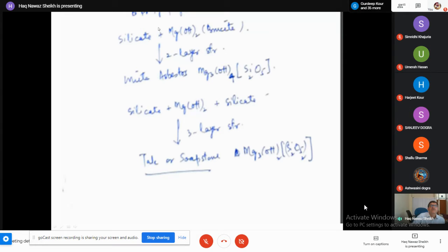So then we have magnesium hydroxide silicates. You can use the aluminum hydroxide layer, or you can use the magnesium hydroxide, because they are isomorphous in terms of the layer form, their ability to form a layer structure. So a two-layer structure is again formed. The formula will be the same again. Si2O5, 2 negative charge here. Now magnesium 3 times, because it is 2 plus.